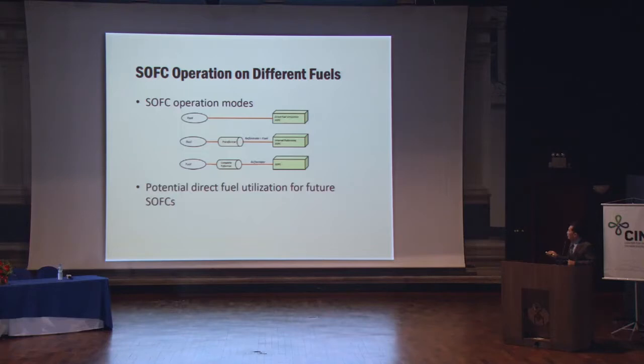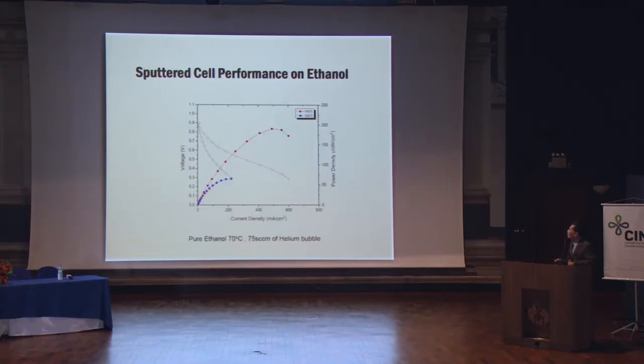We have shown this for the sputter cell, and this one shows the direct utilization of ethanol on the sputter cell at 550 degrees C. As you can see here, we got a very good performance for direct utilization of ethanol at 550 degrees C, close to 200 milliwatt per square centimeter.